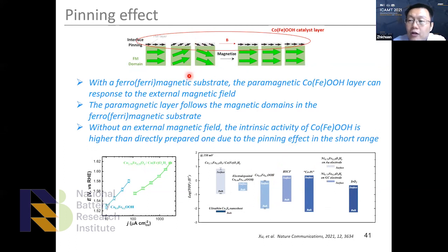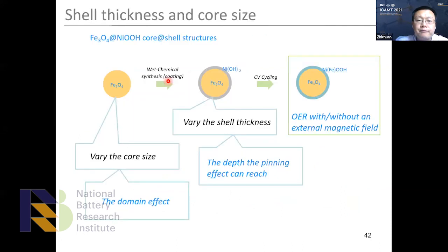So this is meaningful for real applications. For example, we can make core-shell materials in the electrolyzer to promote the reaction. And now we can further investigate some of the science behind it. For example, how the shell thickness and the core size may affect such a pinning effect. So we designed model electrode materials. We use iron oxide particles as a core, and we deposit nickel hydroxide on the surface, and then we do CV cycling to enable the reformation of the surface layer to give the nickel iron oxyhydroxide, which is our catalyst. In this case, we can vary the shell thickness, and also we can vary the core size to see the domain effect, because we know ferromagnetic materials have domains, right?